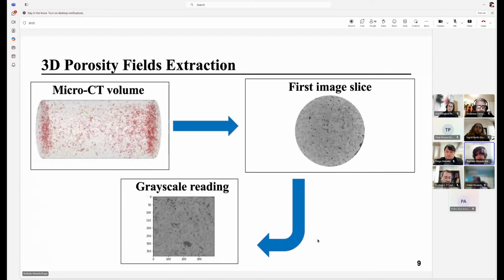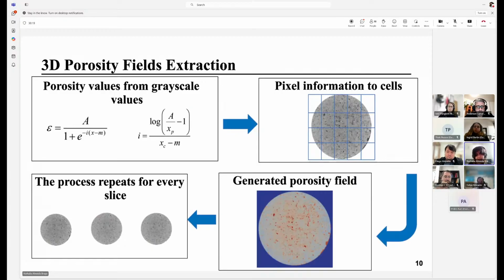So we start with the first slice, and then the algorithm reads all of the grayscale values pixel by pixel from the image. With the full grayscale array, I can calculate porosity values, and these porosity values are approximated by a sigmoid function. It takes into account the grayscale value measured in the pixel, and also maximum and minimum values that I choose for my sigmoid curve.